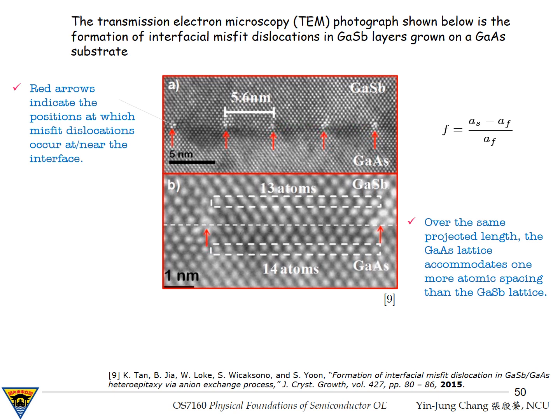These misfit dislocations are line defects. They appear brighter in the image, and in this image they are oriented perpendicular to the page. This periodic spacing is not random. It corresponds to how frequently the lattice must insert an extra atomic plane to accommodate the mismatch.